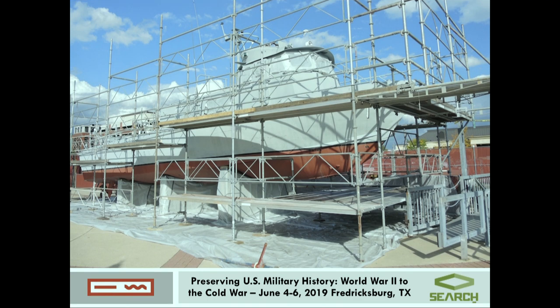And this pure aluminum is protecting the core of your boat, and it's providing cathodic protection during corrosion. So you see where I'm going with that. The way to clean the hull is extremely important, because if you start abrading this protective layer that had already suffered, it would have led to really a more endangered metal after cleaning than it was before.